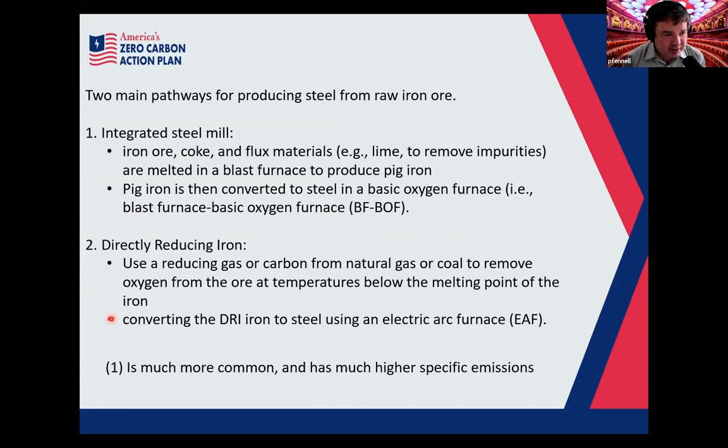The key thing that you need to think about in the future is which pathway we would go for steel production. Would you go for a system where you have the standard, current process, where you're using a blast furnace, etc., producing iron and then transforming that into steel using a carbon-based reductant, a carbon-based material that will pull the oxygen off the iron oxide? Or would you go for a hydrogen-based process which directly reduces the iron, so it takes the Fe2O3 and reacts it with hydrogen, pulling the oxygen off that way? This sounds alluring, and it is in general.